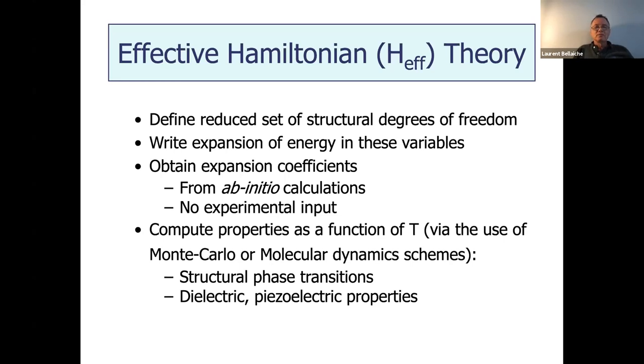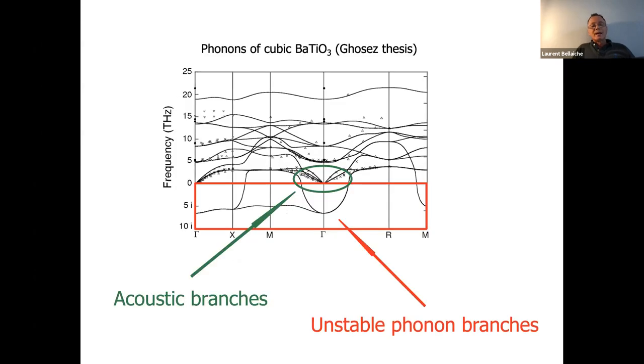When you have the degrees of freedom, the energy and the expansion coefficients, you put them into Monte Carlo techniques or molecular dynamics, and then you can get properties as a function of temperature. You can look at phase transitions. You can look at a lot of physical responses: dielectric, piezoelectric, magnetoelectric, electrocaloric. Really a huge amount of properties can be computed with effective Hamiltonians these days. So what are the important degrees of freedom to understand that?